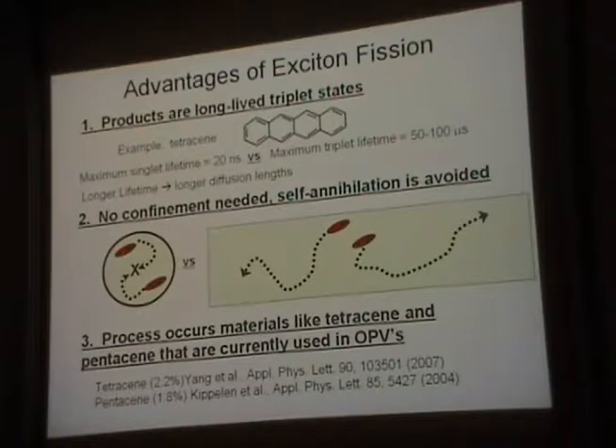Also, it's a bulk phenomenon in these organics, and I'll show you a huge long list of organics where it's a bulk phenomenon. You don't need to quantum confine your excitons into a nanocrystal, right? One of the big problems with multiple exciton generation is you make those excitons at very high efficiency, up to 7 even, but they're all trapped within some tiny ball, and very quickly they recombine, and you lose those excitons. So the time scale that you have to harvest excitons in a nanocrystal is the time scale it takes them to recombine, and that can be 10 picoseconds or 100 picoseconds in, say, lead selenide. Here you don't have to worry about that. You have all kinds of freedom to diffuse away in the bulk. You don't have the same kind of recombination problems that you have for nanocrystals.